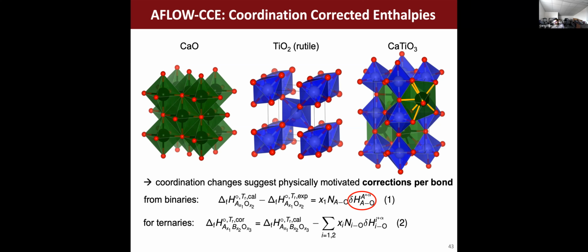So how we extract our corrections is that we look at the differences in the enthalpies between what we calculate with density functional theory and what experiment tells us should be the right enthalpy of formation. We extract a correction which is dependent on the composition and the coordination. We can extract this particular correction and apply it for higher order terms. For the ternaries, for instance, we can calculate a new corrected enthalpy of formation based on our calculations and the corrections we've extracted for the binary systems. That's how our corrections are derived.